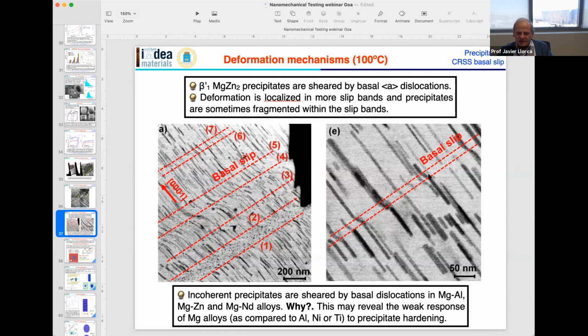And this is regardless of the grain orientation, because the critical resolved shear stress for basal slip is very often one order of magnitude smaller than the critical resolved shear stress, even for twinning or for pyramidal slip. So this process is, I would say, particularly important in the case of magnesium alloys. And that's the reason why magnesium alloys are very difficult to strengthen, because even if you put precipitates, sooner or later they're going to be sheared by dislocations. So that makes strengthening of magnesium alloys difficult.